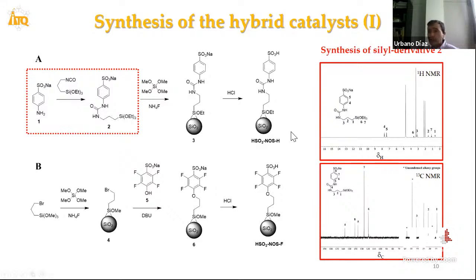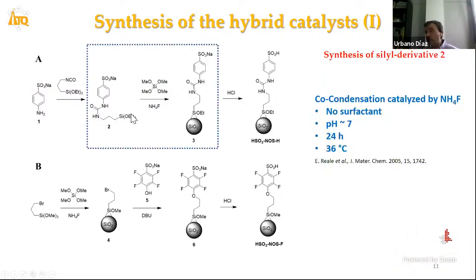The first is the preparation, initially, of this organosilicon precursor, starting from this type of sulfonated aniline molecule reacting with isocyanate groups linked to siloxane units to form this initial precursor. After that, using suitable synthesis conditions in fluoride medium, in absence of surfactants, at neutral pH and practically room temperature, in soft conditions, it's possible to obtain mesoporous non-ordered materials with the presence of the sulfonate groups linked to aromatic units present in the surface walls of the mesoporous materials.